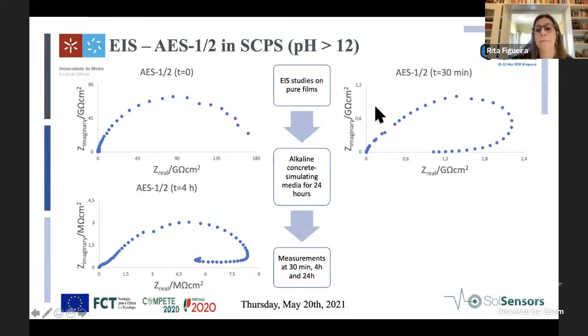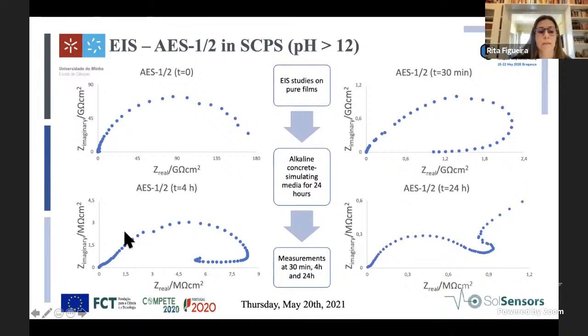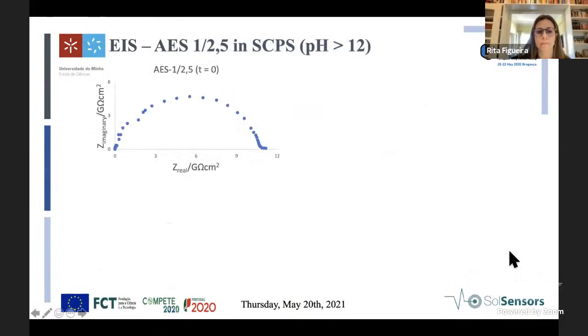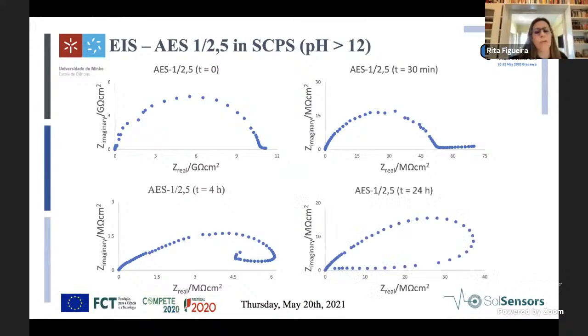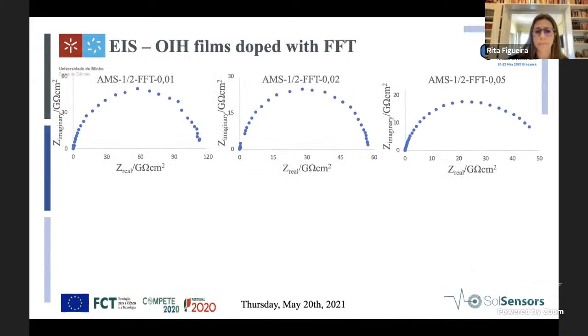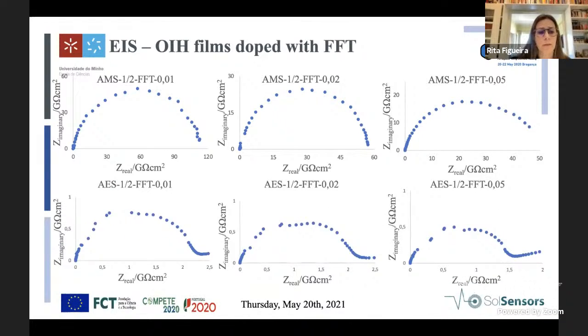And you can see that as time passes, the impedance profiles change. This means that the material is deteriorating. As you can see, the resistance is decreasing with time. We obtained similar results for all the matrices. Also, we saw that the matrices prepared with the same PDMS and different precursors, aminopropyl or aminoethyl siloxane, show different profiles using electrochemical impedance spectroscopy.